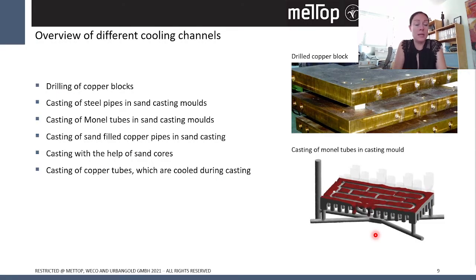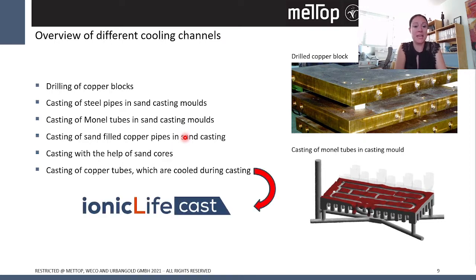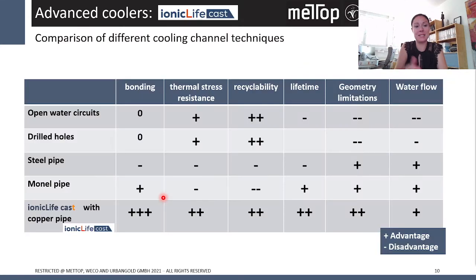So how can you cool any copper cooler? You can either drill the cooling channels in the already casted copper block. You can cast steel pipes, which is actually not very common in use. More common is to cast Monel tubes. So Monel is a copper-nickel alloy. You can also have, as I said before, sand-filled copper pipes during the casting process, which also gives a lot of limitations, since you cannot go too big or geometries are not too easy. You can also cast with the help of sand cores, but the best way to do is to cast the copper on copper tubes. So once again, here we go with our IonicLife cast technology.